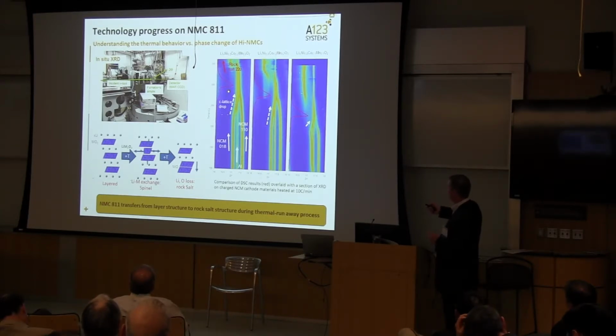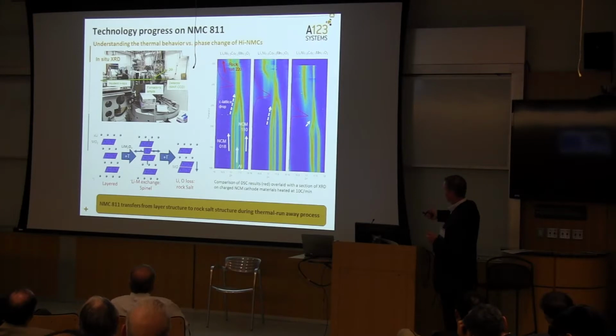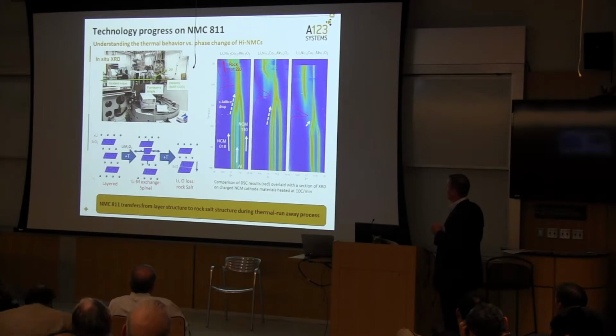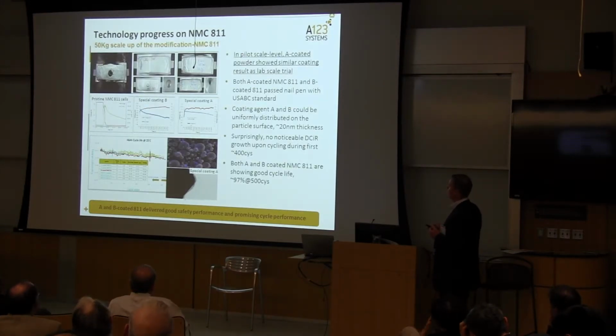This is the onset temperature. We're looking at the DSC result for 50% nickel, and we could see how we could start to look at the C lattice drop corresponding to the DSC result. We know that this cell, when designed correctly, will pass all the abuse tolerance testing. So the key for this program was then to take the NMC at 60 and 80% and shift all of this collapse in the DSC to something equivalent to the NMC 523, and get the same result. And this is what we've been able to do.